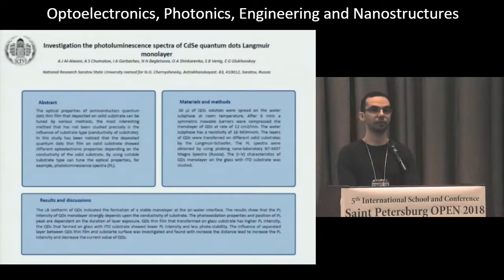The formation of quantum dots monolayer by Langmuir-Blodgett technology. This technology gives us the possibility to control the thickness and the distance between interparticle. The deposition was done on different composition types of substrate. We found that the fluorescence depends on the composition of a substrate because this will influence the energy transfer from quantum dots to the substrate.